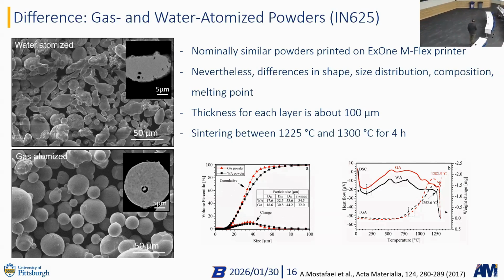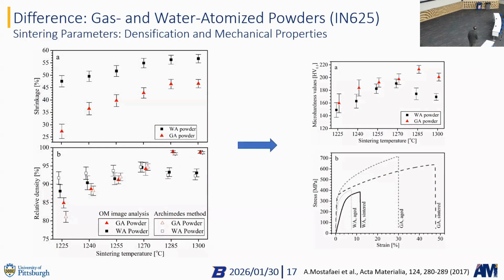So we wanted to figure out what's actually the difference between the two, and can we use them in binder jet printing independently? So we did a sintering study. You see here, we heated our materials up to the same temperatures, right? And then looked at how do they actually densify. So we saw that in gas atomized powder, which is the spherical one, we see really nice densification up to nearly 100%.